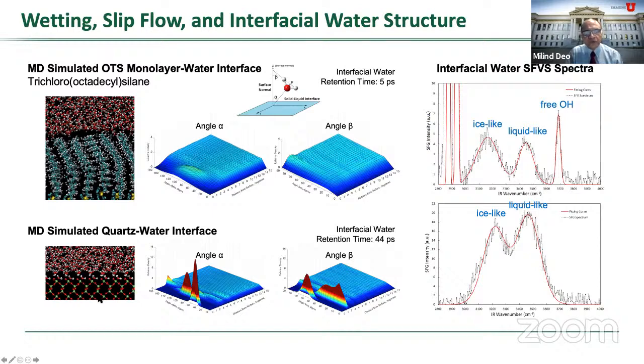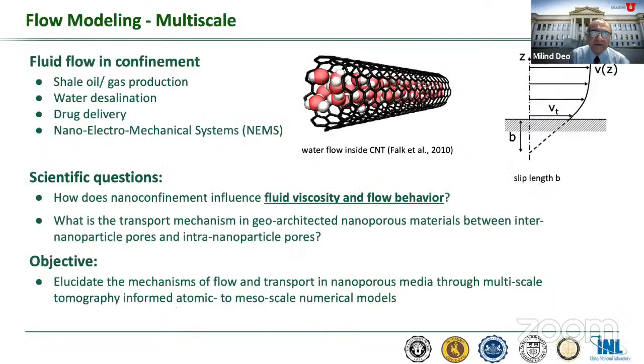So we see an exclusion zone here for the hydrophobic surface, and more or less for the dipole angle, we see essentially a fairly ordered structure for the hydrophilic systems and a free OH layer for the hydrophobic systems. And that's again confirmed using sum frequency vibrational spectroscopy. So again, quite a bit of evidence from different surface materials and different experimental systems.